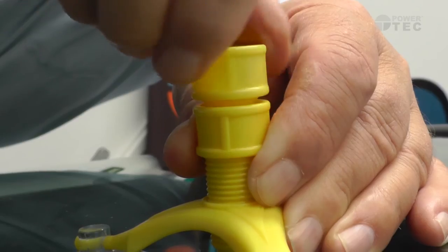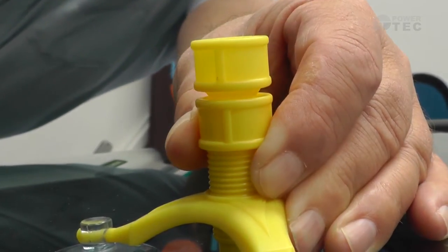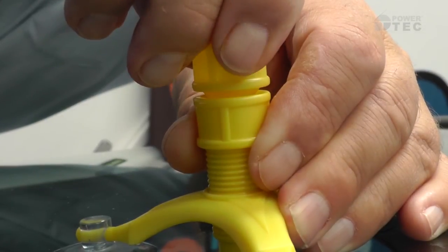After three minutes or so, release the pressure by one full turn to drive out any remaining air, then apply pressure again.